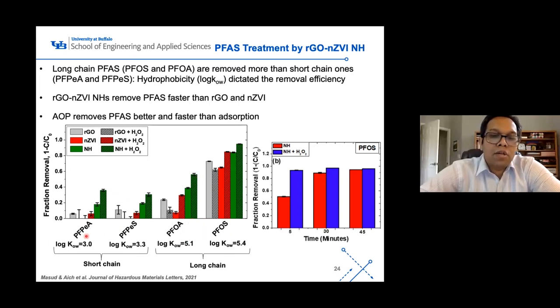So the major thing is that with increasing carbon number, their hydrophobicity or log KOW values increase. So they become more attached to the graphene structure, which is the graphene backbone in the rGO-nZVI nanohybrid, which is hydrophobic, right? Which is carbon-based. So that's why we see more removal of larger PFASs than smaller PFASs. The other thing we saw is that if you look at the nanohybrid peaks compared to the single nanomaterials like RGO and NZVI, nanohybrids remove PFASs faster than the graphene or NZVI.